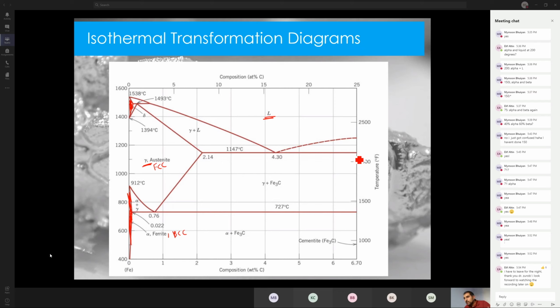And there's actually one phase that's hard to see. It's this compound, Fe3C. Now it's a compound, so it has a very determined stoichiometry. It doesn't have any width to it. It has to be exactly 25 atom percent. So up here is the atom percent. Here is the weight percent. It's exactly 25% carbon and 75% iron. So it shows up as just a thin line on the diagram. So this thin line is the cementite.